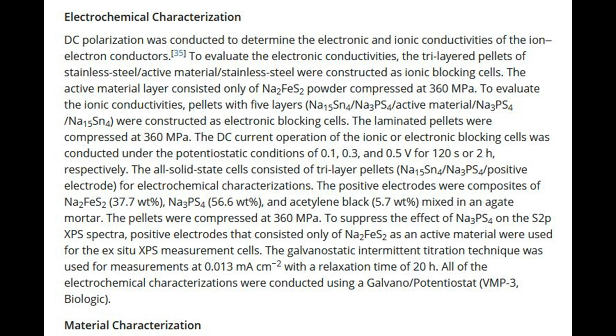To suppress the effect of Na3PS4 on the S2p XPS spectra, positive electrodes that consisted only of Na2FeS2 as an active material were used for the ex situ XPS measurement cells. The galvanostatic intermittent titration technique was used for measurements at 0.013 mA/cm2 with a relaxation time of 20 h. All of the electrochemical characterizations were conducted using a galvano/potentiostat, VMP3, BioLogic.